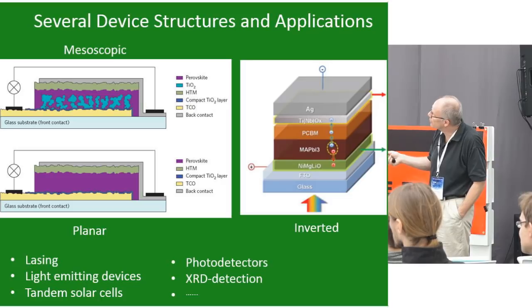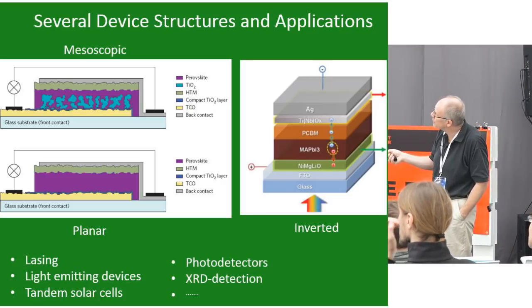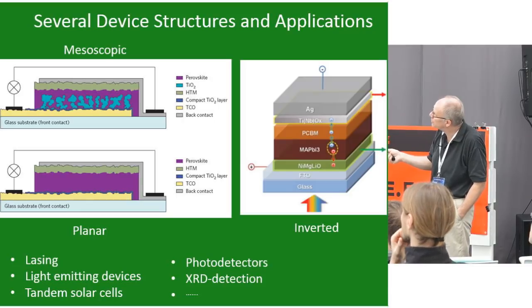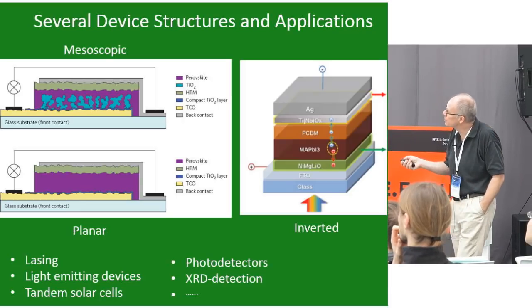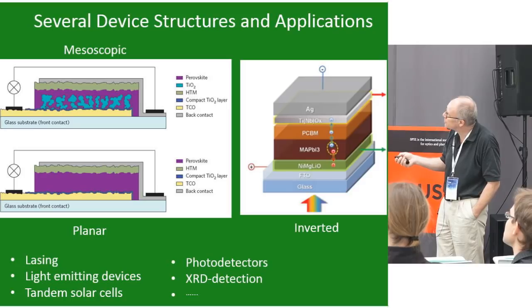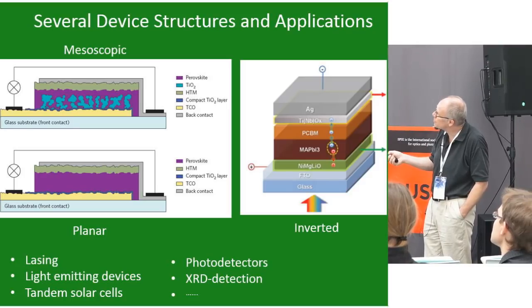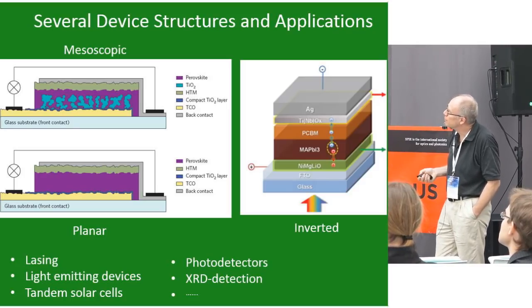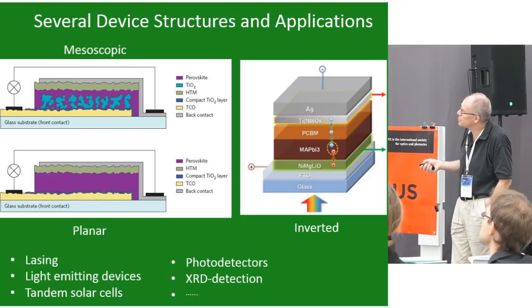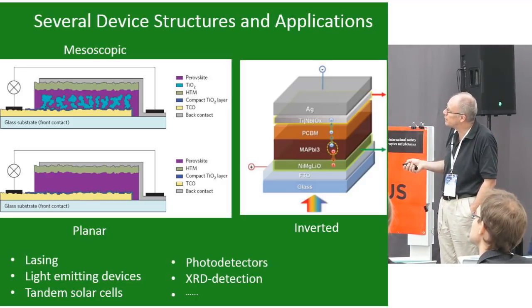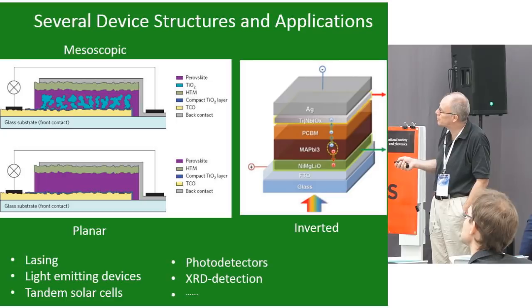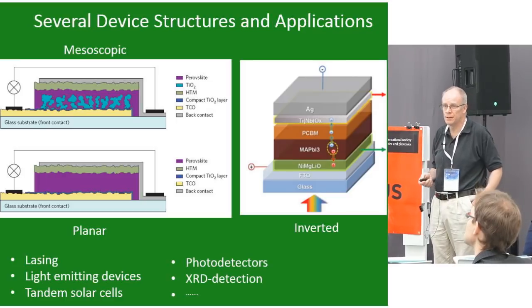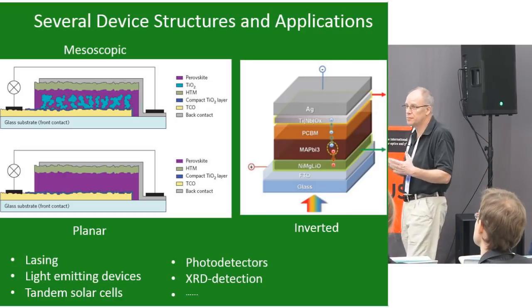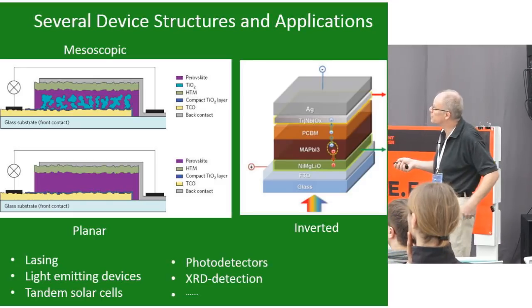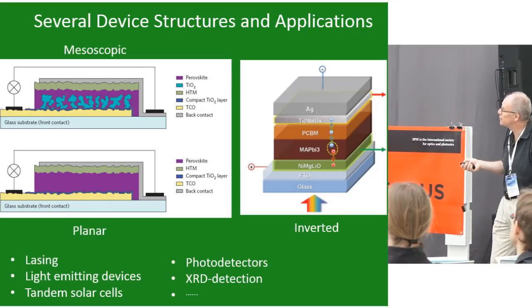Then you have it on the contact, and you have then spiro, for example, as a hole contact, and then you put gold as a contact on the top. So you excite the perovskite, the electron goes to this side, and the hole goes through the spiro to the gold. But perovskite can conduct electrons and holes on its own, so you can basically take an electron contact and a hole contact and put perovskite in between, and they work as good, I would say. So that's the simplest structure and very exciting for practical reasons.